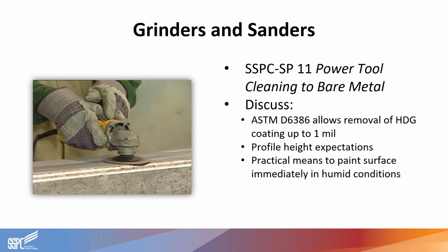So grinding zinc, for example, doesn't produce any sort of sparking. So if you do see sparks with the use of grinders and sanders related to galvanizing, it means you've somehow made it all the way down to bare metal. ASTM D6386 does allow up to 1 mil reduction in coating thickness if this method is selected. So again, that's another topic that should be evaluated on a project basis. Grinders and sanders also produce significant zinc dust on the parts in comparison to other roughening methods. So this can lead to more rapid zinc oxide formation in humid conditions. So you want to make sure that if this is going to be used, there is a way to get from surface prep to painting as soon as possible.